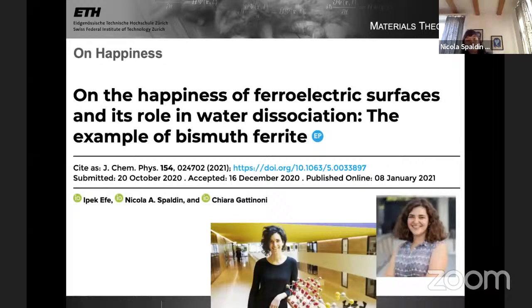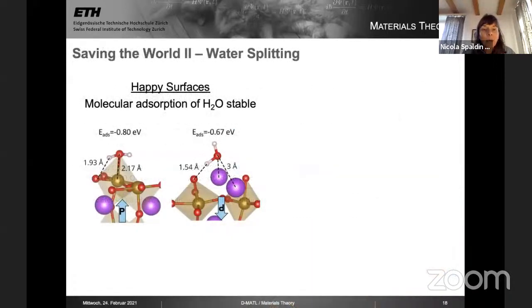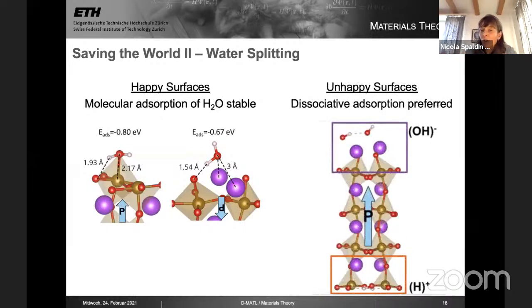Okay, so on happiness, we can now use this happiness and unhappiness of the bismuth ferrite surfaces to dissociate water. And this is work from Chiara Gattinoni and Ipek Efe And so what we find is on a happy surface, again with our density functional calculations, and this will also allow us to save the world, of course, because we can generate hydrogen with this. On the happy surface, which is charge neutral, then the molecular water tends to adsorb, whereas on the unhappy surface, which is very highly charged, dissociative adsorption of OH minus or H plus is strongly preferred.